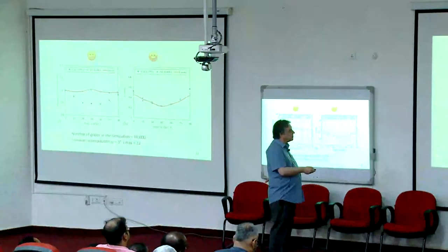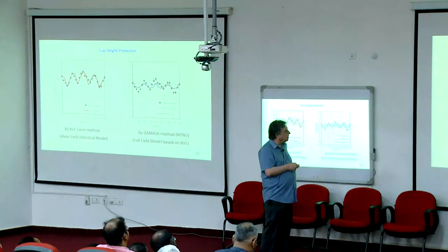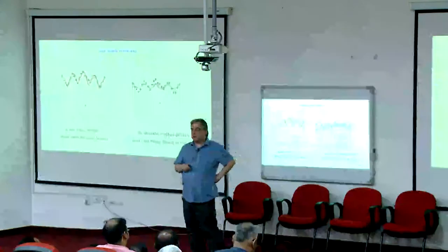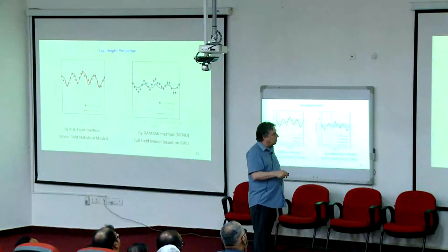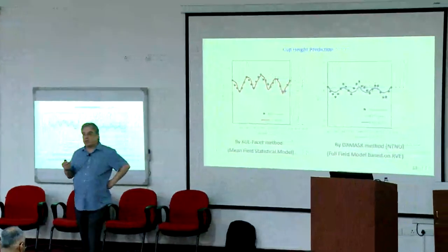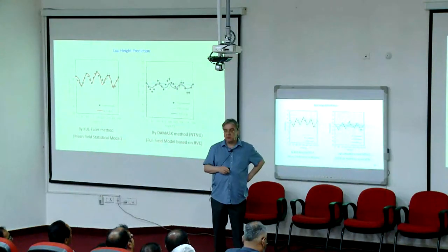We try various things, but on the basis of this crystal plasticity method, we also try to model the cup heights, this cup earing you see, and how close it is: the experimental data and the prediction on the basis of a statistical model. This didn't take 3 weeks of CPU time. This took less than an hour of CPU time just to calculate it. So that is industrially much more relevant. And at least in this case, I'm not going to generalize this, we were even more precise than a full crystal plasticity simulation based on RVEs. Even if these were equally correct, this would again take weeks of CPU time, and this less than an hour. So that's really an important, powerful way of dealing with microstructure.